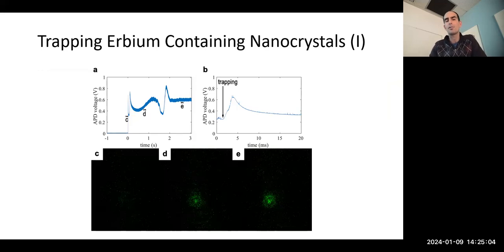One interesting thing about these erbium emitters is that they allow for upconversion, meaning that with our 980 nanometer trapping laser, this erbium ion will absorb multiple photons and then emit light in the green, blue, and red. So you get multiple emission peaks from this single ion. This makes it possible to see these emitters even though they're emitting in the infrared—we can see the visible emission from them, which is a nice property.